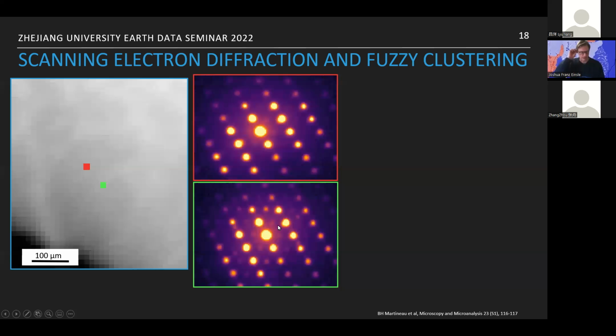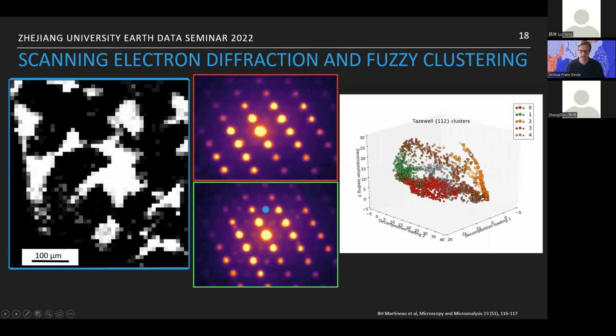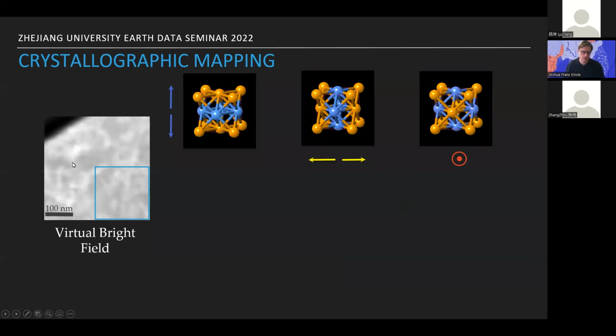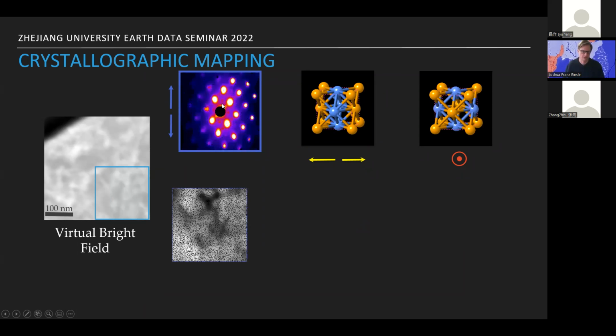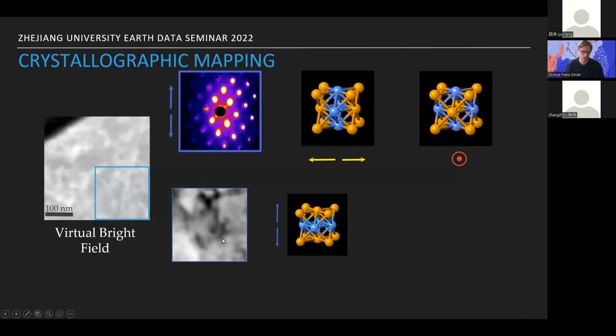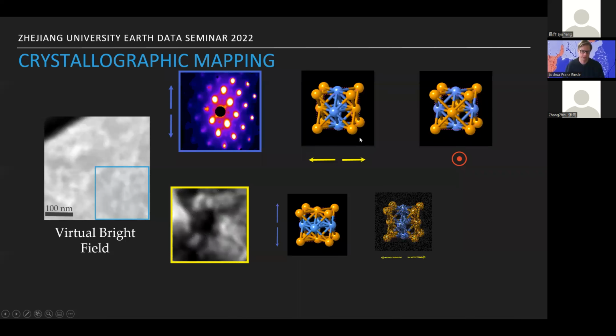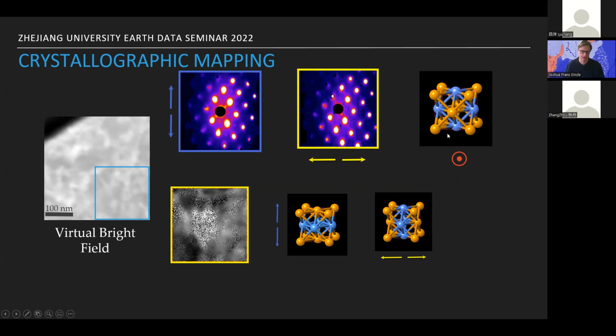So what we did is we performed a dimensional reduction using PCA, to first reduce the overall number of dimensions of the problem to about 5, and we then threw it into a clustering algorithm. We could then project these 5 clusters into a data space described by the decomposition, and we can see that it starts to form about five groupings, depending on how you look at it. Doing a clustering like that, initially looking down the 100 axis, we can identify in the tetrataenite the first diffraction pattern here, where we have this symmetry, and we get this loading map, this distribution of grains. We then look at the second diffraction pattern, and finally the third diffraction pattern.